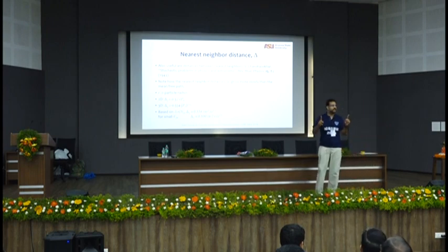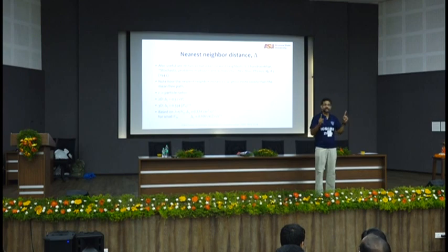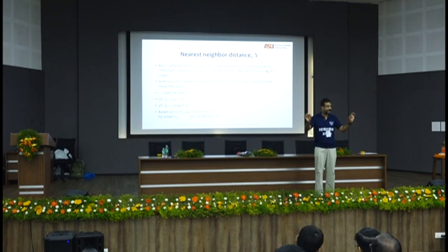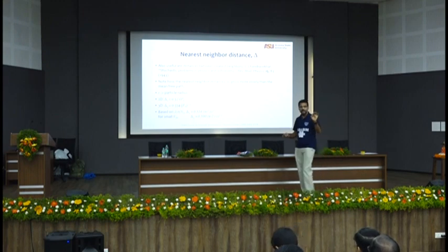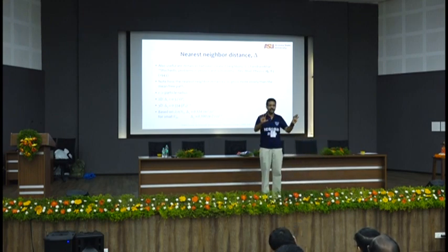When synergies start to get disturbed, that's when problems start. Corrosion is a classic example of disturbance of synergy. You remember the passive layer around steel that you want to have? That's a layer which is stable at high pH. The moment pH drops, that layer breaks. The synergy is on as long as the pH is high. When a chloride ion comes in, or when moisture comes in and breaks the synergy, that pH goes down, that layer starts to break, and then corrosion is very, very fast.